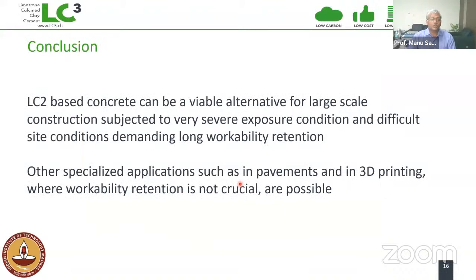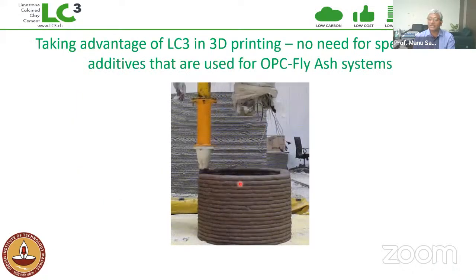So just to conclude, LC2-based concrete or LC3-based concrete can be a viable alternative for large-scale construction, subjected to very severe chloride exposure, and even in site conditions that demand long workability retention. In both those sites that I showed you, we got very good retention for at least 2 hours, and that was good enough to actually execute those projects. There are obvious choices where we don't really have a problem of workability retention, for instance, pavements, and even in 3D printing, where the loss in workability can be quite a positive aspect. And I can show you some examples of 3D printing with LC3 concrete.